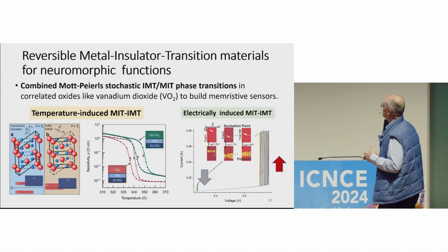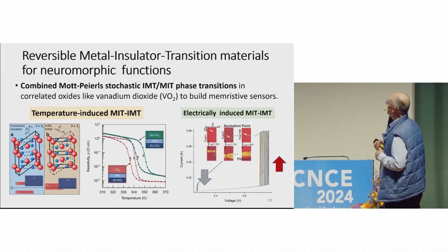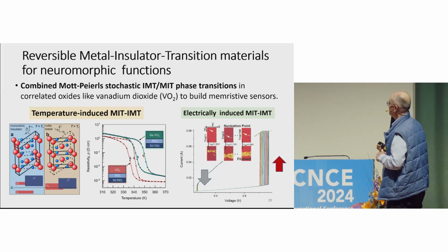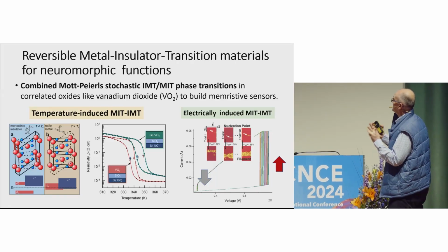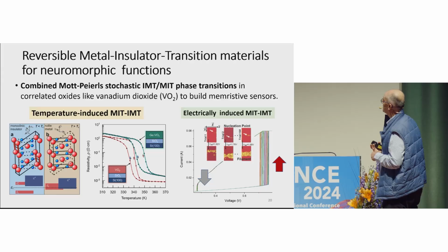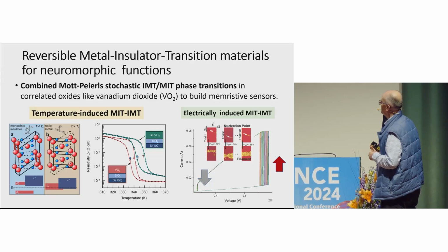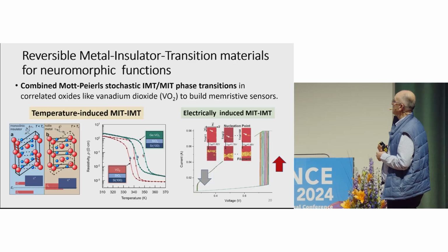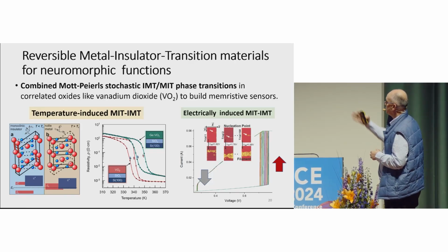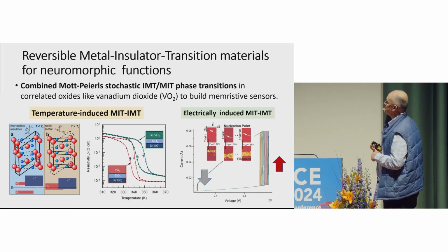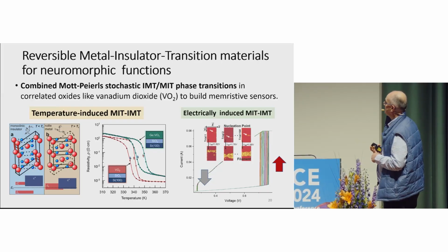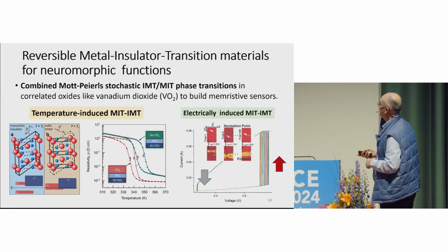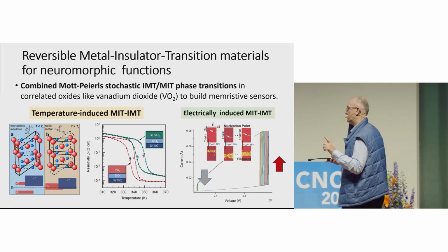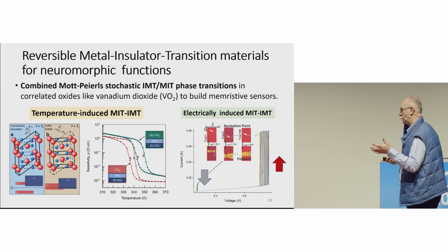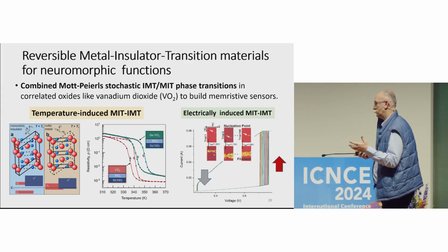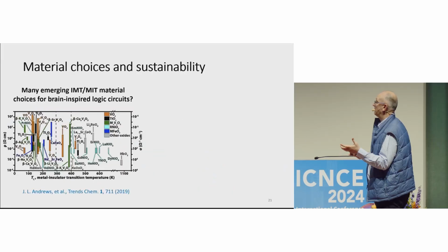And people show that an electrically induced reversible metal-insulator transition can happen, practically by the creation of a filament of conduction. And if you design the film properly with a certain dimension, at a certain thickness, you can achieve, like in my plot here, a hysteretic curve in a memristive behavior that here is non-volatile below 1 volt. So this is what we want to use, and to say now, if we make a memristive type of device based on this, it will be extremely sensitive to your environment.